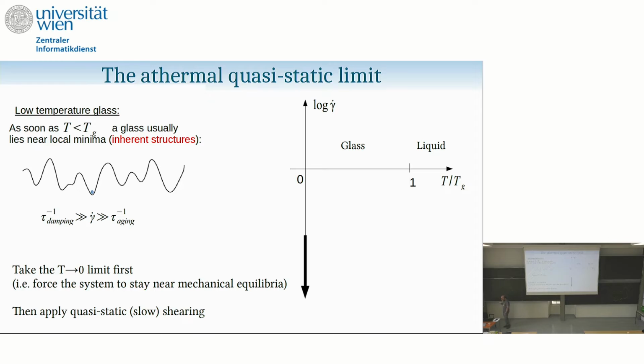So the idea of the athermal quasi-static limit is to find a way to avoid the problem of timescales. The idea is that, as I said, if we are in a glass, in a solid, at really low temperature, so you are very far below the glass transition temperature, your solid essentially is quenched, trapped in a single local minimum of the potential energy landscape. And the thermal fluctuations are completely irrelevant. So you no longer need to simulate the thermal fluctuation. The only thing you need to know is where your local minimum is.